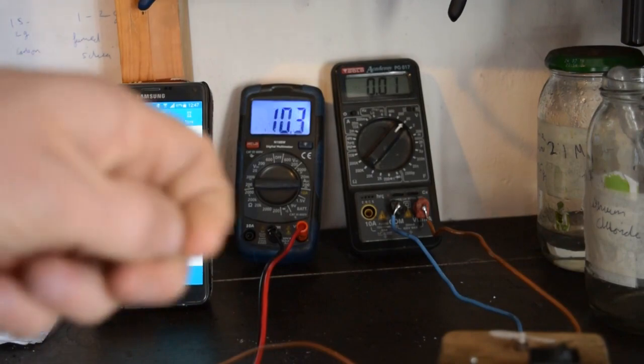So it lasted about 8 seconds. So from watching back that video, I made a calculation of 7 watt-hours per kilogram of the active material. Now, of course, you can watch back that video yourself and make your own calculations and see whether my maths is up to scratch. Now, 7 watt-hours per kilogram of active material is quite good. It's nowhere near Robert Murray-Smith territory, but it's quite good when you consider that it's a water-based electrolyte. We're only charging it to 1.6 volts, and it's just a basic symmetric supercapacitor.